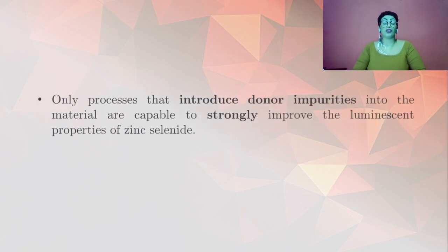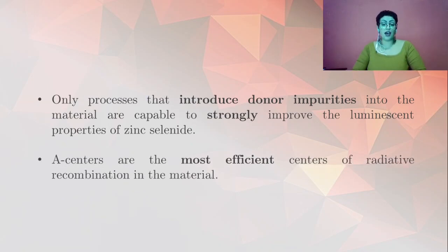As a result, this work demonstrates that only processes that introduce donor impurities into the material are capable of strongly improving the luminescence properties of zinc selenide. The implication of this result is that the complex defects involving donor impurities and zinc vacancies, A centers, are the most efficient centers of radiative recombination in the material.